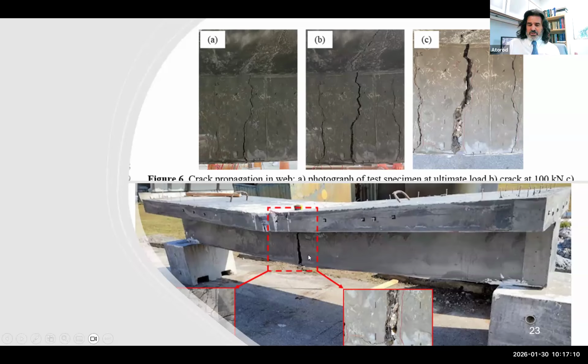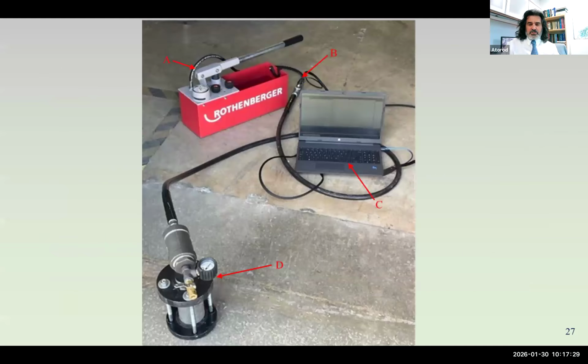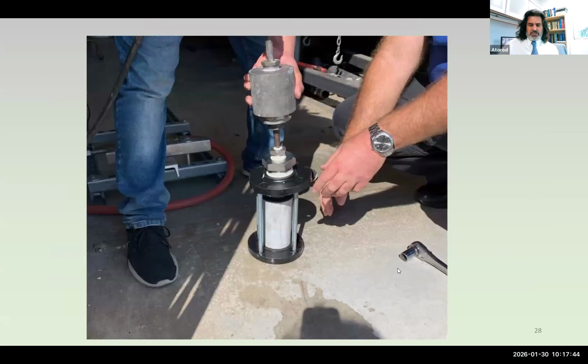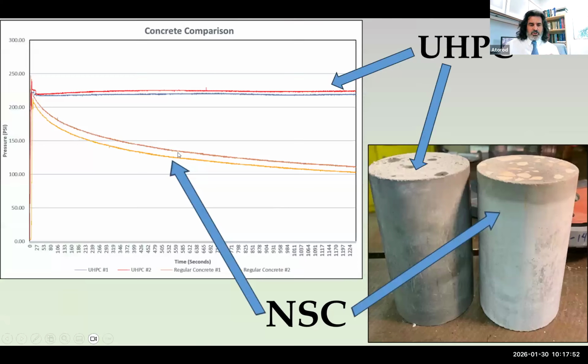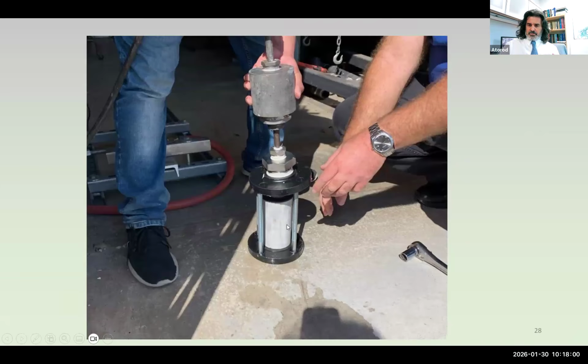Let me give you some idea on durability. We have developed techniques that in 10 minutes you can evaluate the relative durability of different types of concrete. What we do is take a cylinder and apply very high water pressure to it, and then watch how the pressure changes over time. One foot of water creates about 0.433 psi pressure. So if I apply 200 psi pressure on top of that cylinder, that will be similar to putting that cylinder under 460 feet of water.